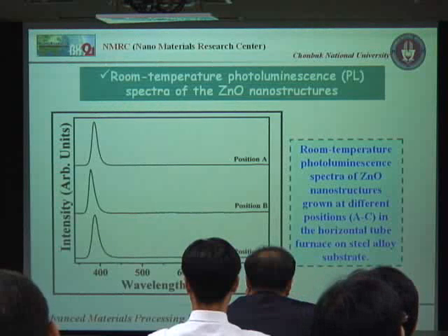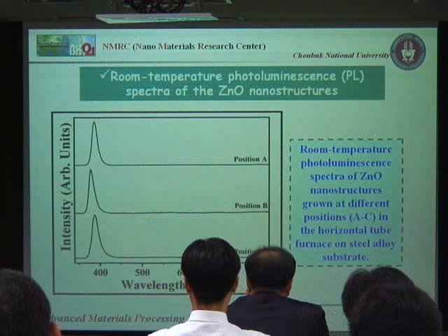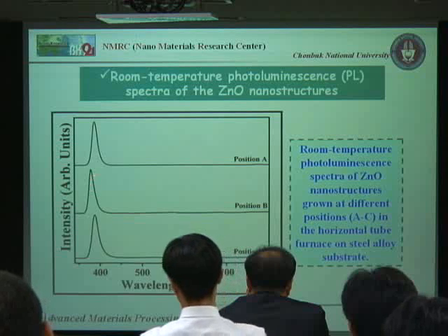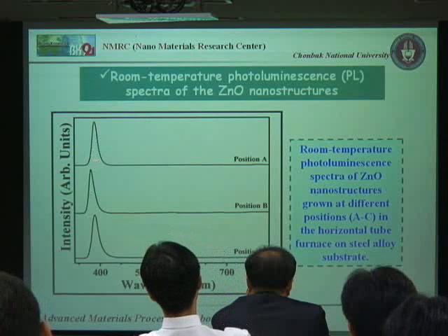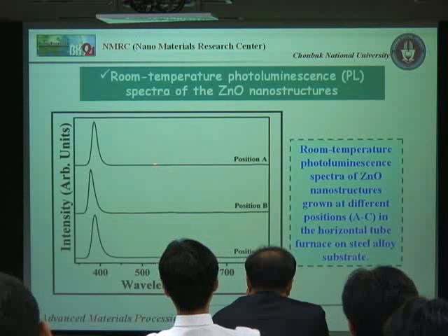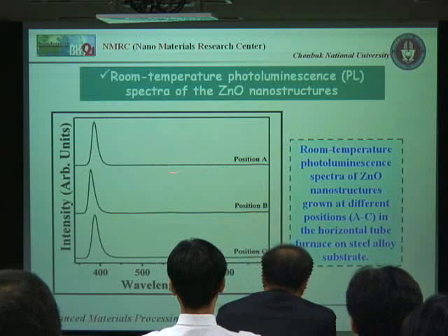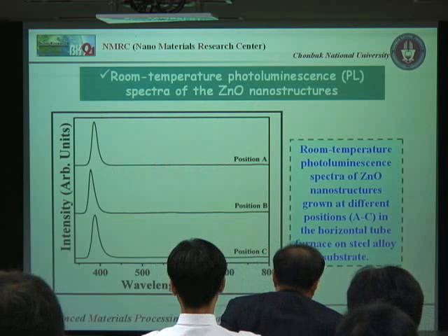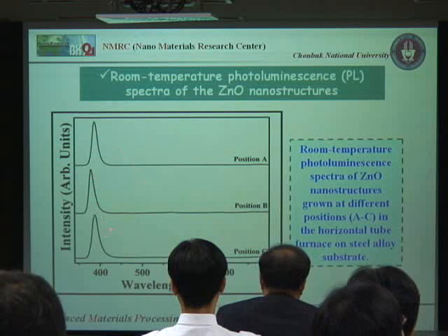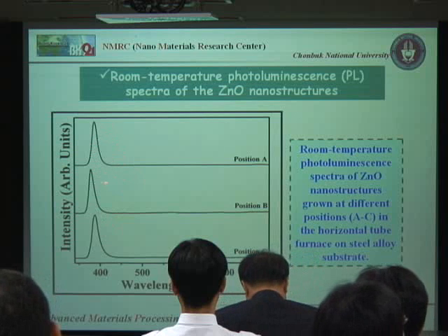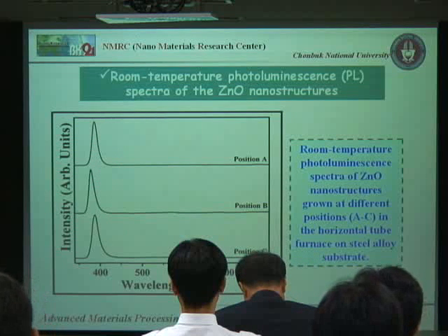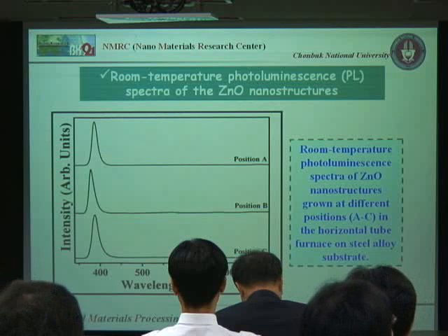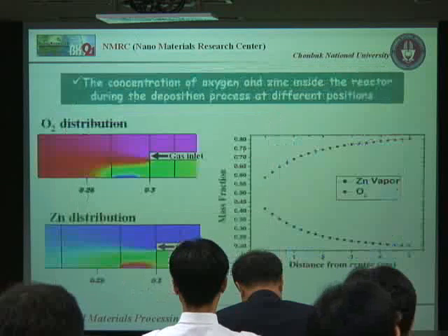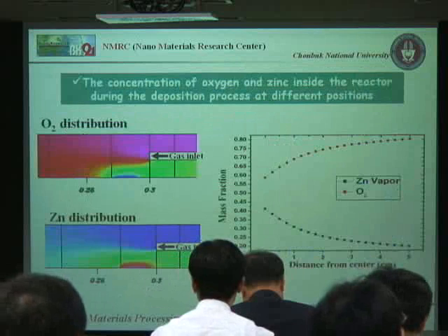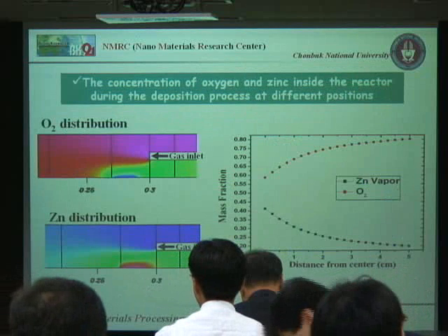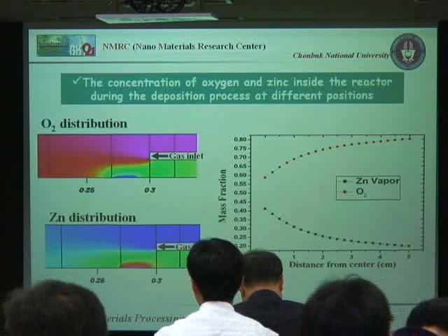In room temperature photoluminescence spectra, we only got a strong and sharp UV emission in all the cases, without any green emission or different emission. From this room temperature photoluminescence spectrum, we can confirm that our grown nanostructures have excellent optical properties and very few structural defects.